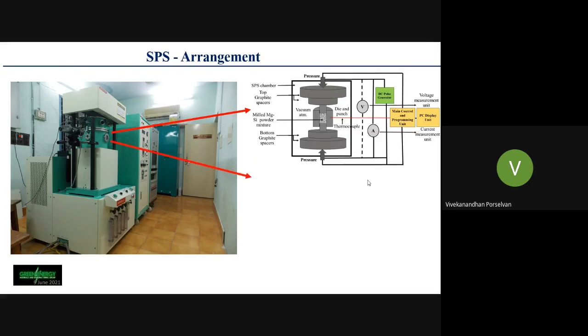So this is a spark plasma sintering instrument. Here the main advantage of this particular system is that the heating rate will vary between 800 degrees Celsius to 1000 degrees Celsius per minute. Whereas in the conventional case, we have the limitation of maximum 10 to 15 degrees Celsius per minute. So see the difference: 15 degrees Celsius per minute in conventional methods, and 800 to 1000 degrees Celsius per minute in the spark plasma sintering instrument. Thereby, it is one of our most advanced sintering furnaces, which will help you to retain the nanostructured material.